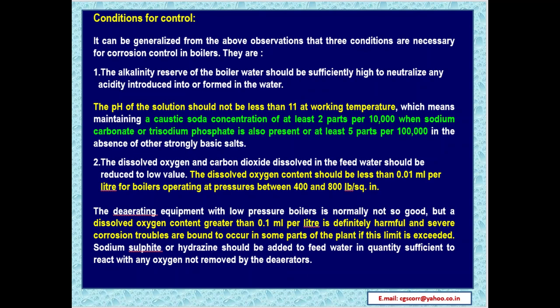Conditions for control. It can be generalized from the above observations that three conditions are necessary for corrosion control in boilers. They are: the alkalinity reserve of the boiler water should be sufficiently high to neutralize any acidity introduced into or formed in the water. The pH of the solution should not be less than 11 at working temperature, which means maintaining a caustic soda concentration of at least 2 parts per 10,000 when sodium carbonate or trisodium phosphate is also present, at least 5 parts per 1 lakh in the absence of other strongly basic salts.